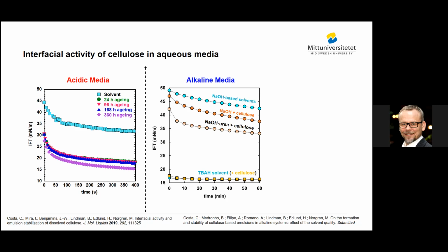significant drop. And this significant drop is due to, of course, that the cellulose has a lowering effect on this interfacial energy, which makes it go to the surface between oil and water, or oil and acid, to lower it. And that tells a lot about its amphiphilicity.